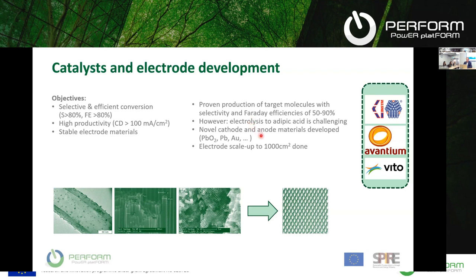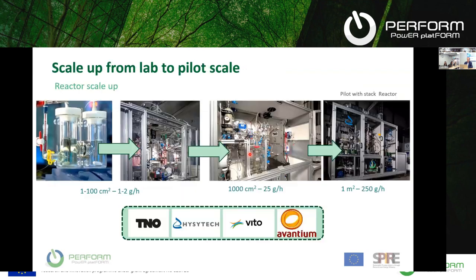On the other hand, we did work on novel cathode and anode materials for the other reactions, and we also proved that we can do electrode scale-up to a 1,000 square centimeter electrode. So this is how scale-up works. You start very small in electrochemistry, and then you go to bigger steps, bigger reactors. And this was 2 years ago, and now we're here.